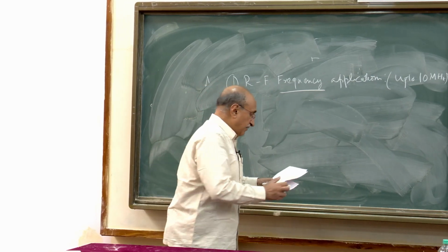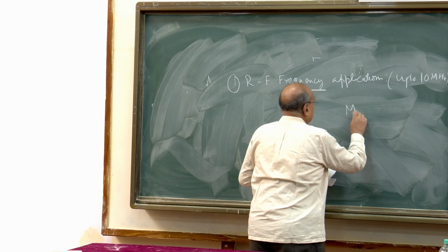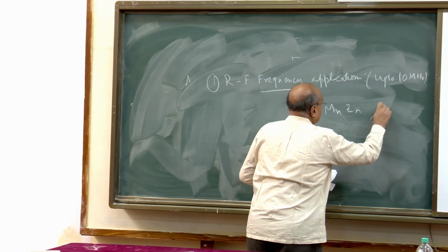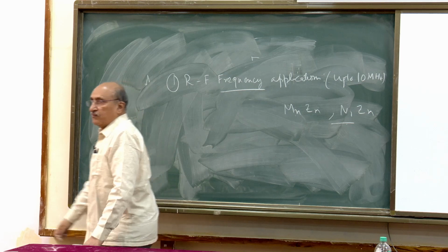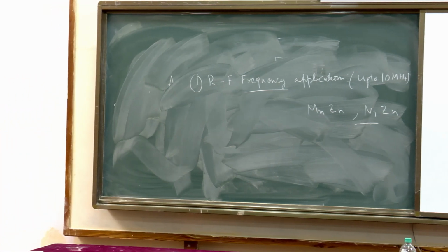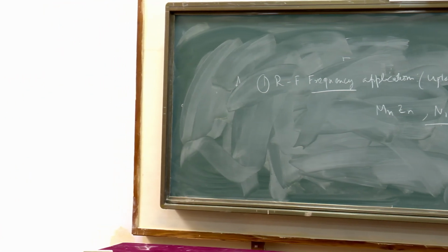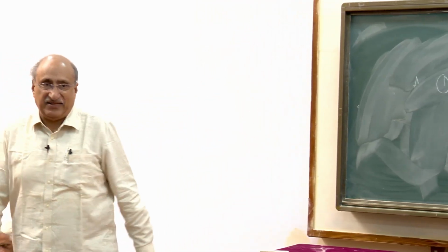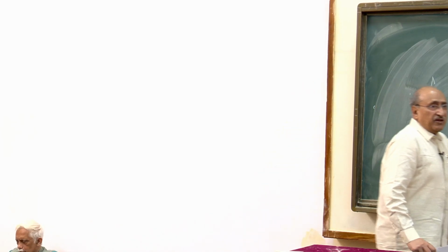So there are ferrites like manganese zinc ferrite and nickel zinc ferrite, which have been developed for these frequency ranges. They have generally one of the highest magnetizations in normal ferrite systems, but they do not have a very, very high resistivity.